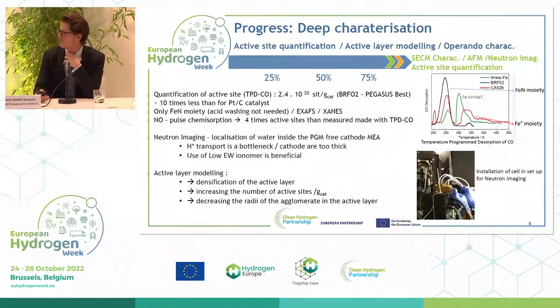Then we also performed neutron imaging to better understand where the liquid water condenses in our active layer. So that was very nice and tiring sessions to be able to do that, but it was fun to do. We also used a low equivalent weight ionomer, and we saw that it's beneficial with this kind of material, with this kind of carbon support, to be able to enhance the performance of our catalyst layer.